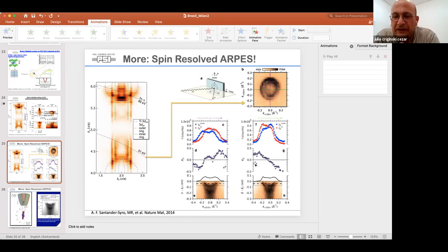Yeah, indeed. If I remember correctly, in the case of some titanates, the beam catalyzes a reaction that breaks the carbon monoxide that normally sticks to the surface, and then it evaporates. Exactly, so this is a good situation. Normally you just get carbon adsorbed, but in that case it's a catalytic reaction that breaks the carbon monoxide and it evaporates. It's a fortunate case, yes.